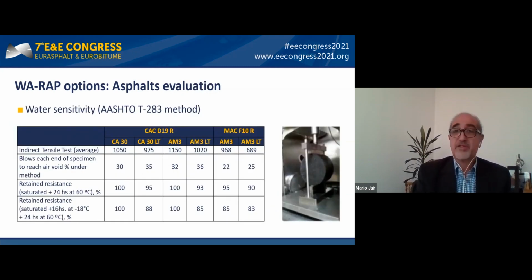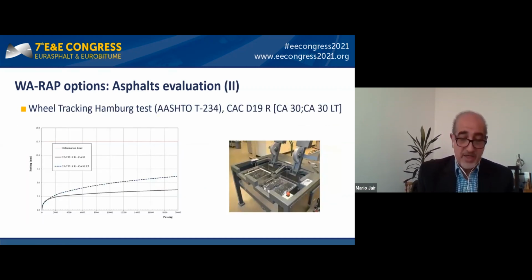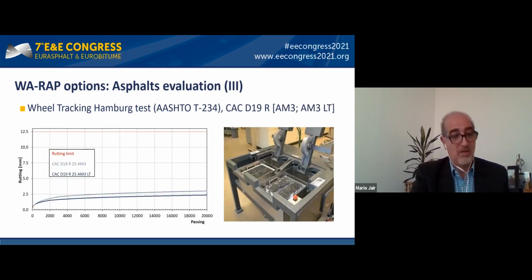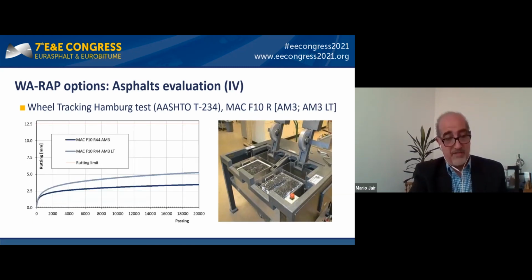Starting with the evaluation of the designed warm RAP options, we decided to observe the resistance to water, which was evaluated by means of the indirect tensile test. As can be seen, the retained resistance was greater than 80% in all cases. We also decided to study the rutting performance using the wheel tracking Hamburg test. The slide shows the behavior for the dense mix with conventional binder and its low temperature version. Here, for the same asphalt mixture, but based on AM3 and AM3 low temperature. And finally, the thin asphalt mixture based on AM3 and AM3 LT.